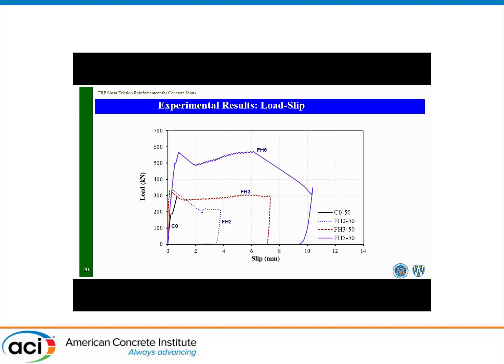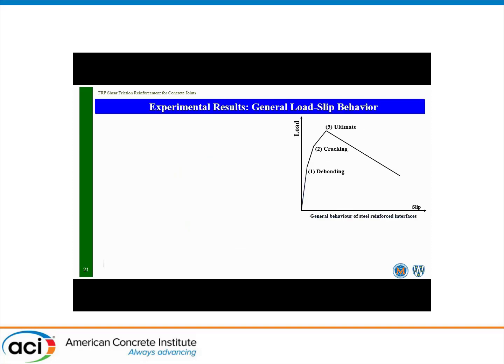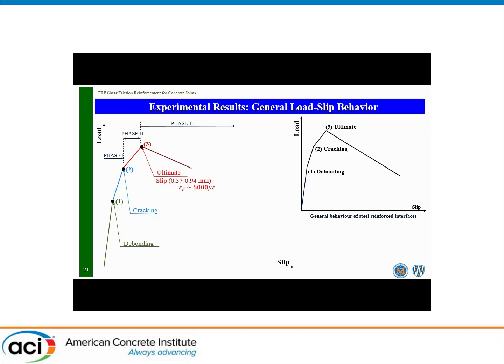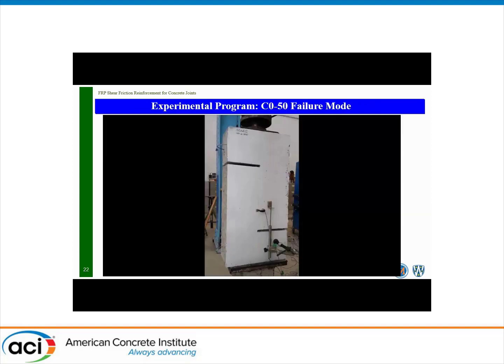That's why they didn't show significant increase in strength after the crack initiated, while GFRP headed bars show significant increase. If we look at the overall load-slip behavior for the FRP reinforced interface, it's very comparable to the steel one, but they have a more significant advantage: they are able to sustain much higher levels of load after the initiation of the crack due to the linear behavior of the GFRPs in general.